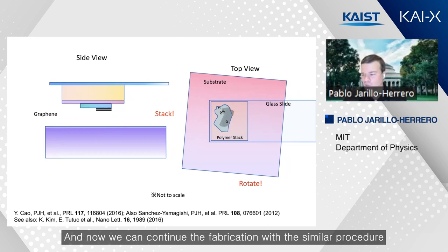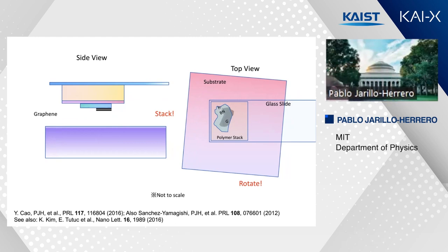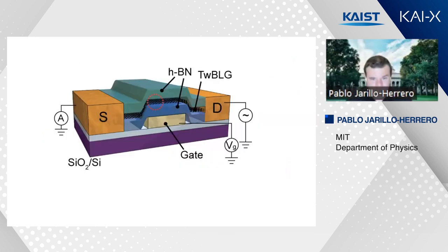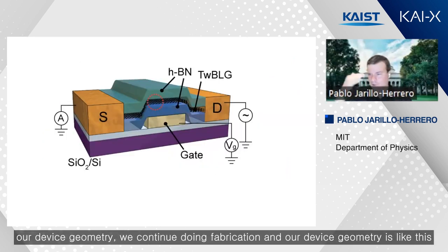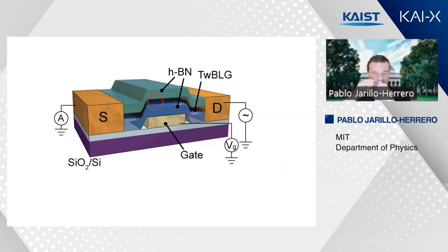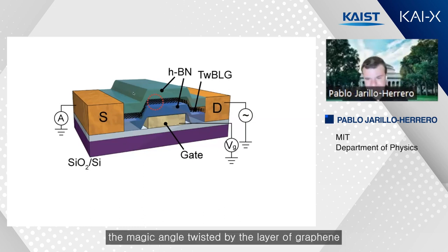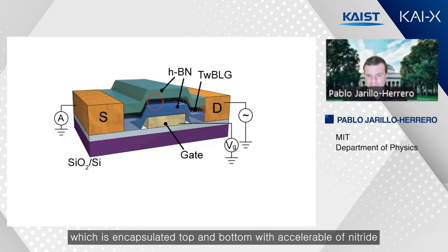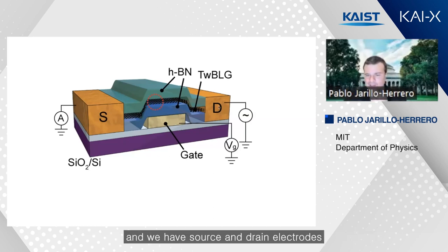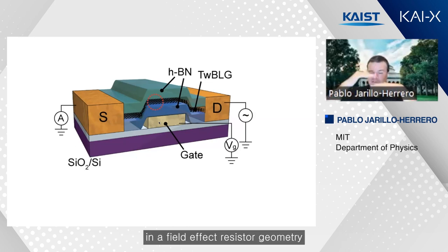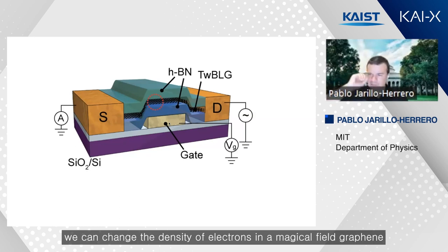And now we can continue the fabrication with a similar procedure. So we continue doing fabrication, and our device geometry is like this. We have the magic angle twisted bilayer graphene, which is encapsulated top and bottom with hexagonal boron nitride, and we have source and drain electrodes. And then we also have a nearby metallic electrode in a field effect transistor geometry. So with this metallic electrode, we can change the density of electrons in the magic angle graphene.